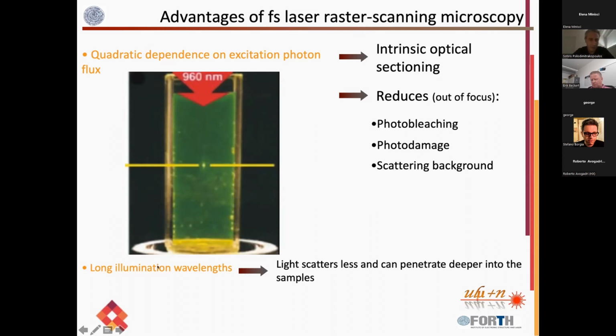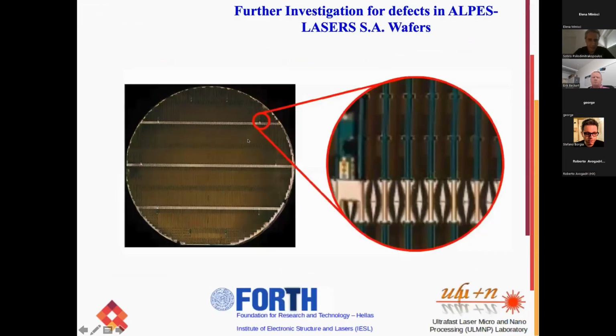Because we are using IR, long illumination wavelengths, we can go much deeper into the sample. We can reach approximately 1 millimeter depth in highly scattering samples by using this femtosecond laser and this raster scanning technique.